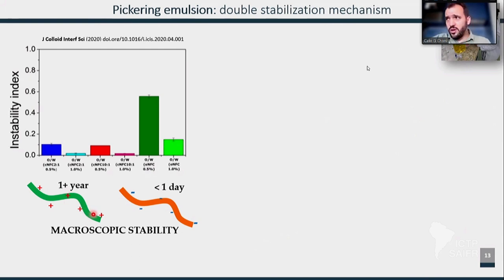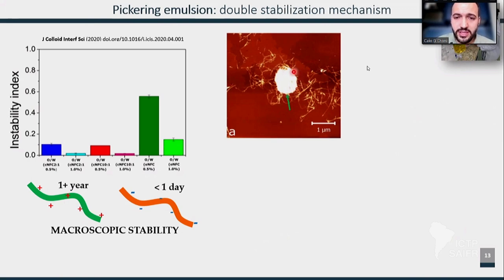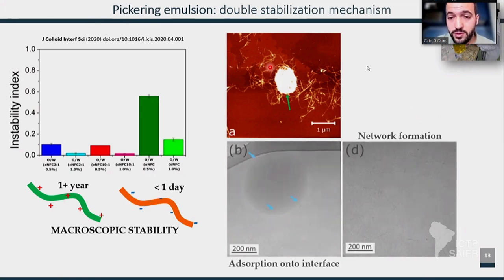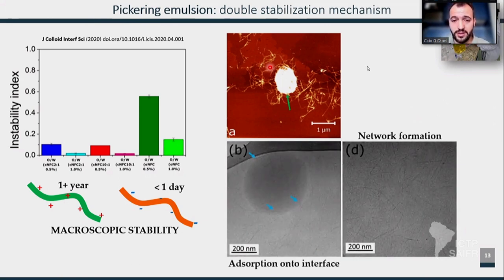And the cationic species are still sitting on the bench with macroscopic stability. Why, right? So we went for AFM and we could see that the droplets were completely coated by these cellulose nanofibrils. But they were not only in the interface, they were also in the bulk. But of course, AFM has to dry the sample, and then we went for cryogenic TEM, right? Cryo-TEM. And we can see a double stabilization mechanism. So a particle sitting in the interface, and this is easy to see from interfacial tension experiments, and also a network formation in the continuous phase, so thickening the continuous phase. This is something that is interesting for stabilization of multi-phase systems.